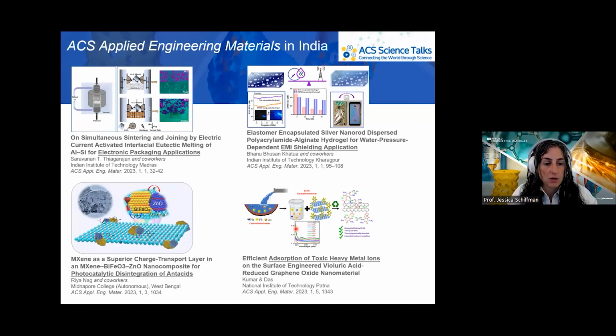In our case, it was quite interesting. For example, when we looked at membranes, if we used a molecular weight that was too long, it would inhibit the flow of water through the membranes and clog the pores. So for that case, we had to stick to a shorter backbone, maybe 5K, 20K also works, something like that.